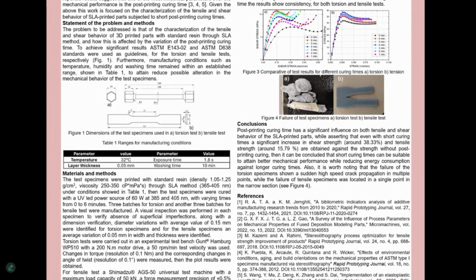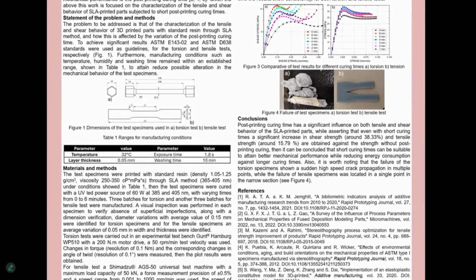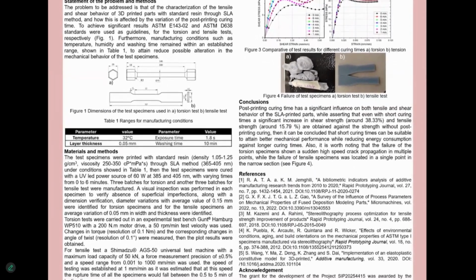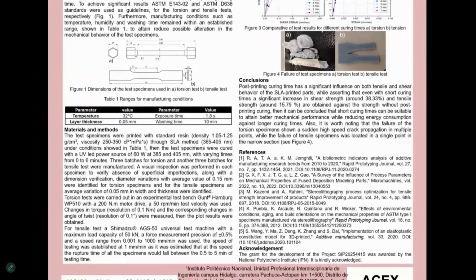Then it can be concluded that short curing times can be suitable to attain better mechanical performance while reducing energy consumption against longer curing times. Also, it's worth noting that the failure of the torsion specimens shows a sudden high-speed crack propagation in multiple points, while the failure of tensile specimens was located in a single point in the narrow section of the test specimens.